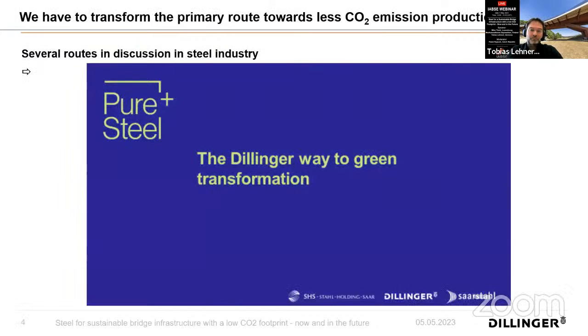And that means we also have to transform the primary route towards less CO2 emissions. And Mike explained also the possibilities there, for example, by going to a DRI production, direct reduction, plus electric arc furnaces. So there exist several routes in the steel industry which are currently followed. We have also a brand for our transformation. It's called Pure Steel Plus, and that's our way to transform our company to a low-emitting steel production company.